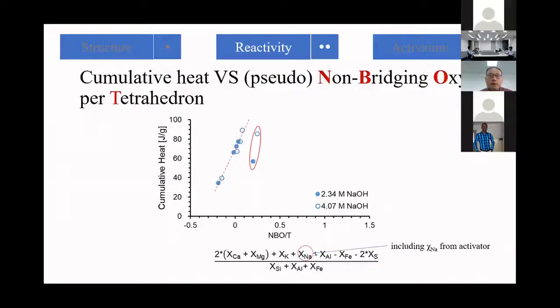This pseudo non-bridging oxygen per tetrahedron parameter is not only applied to slag, but it also applies to fly ashes. Only for some fly ashes with very high iron content does it not follow this parameter, but for the other fly ashes, it can be clearly seen that this parameter correlates well with the cumulative heat. In other words, for this kind of fly ash, it makes no sense to increase the alkalinity since its reactivity is quite low. It cannot be enhanced only by alkaline solutions. For this kind of fly ash, it's suggested to use, for example, elevated temperatures to increase its reactivity.